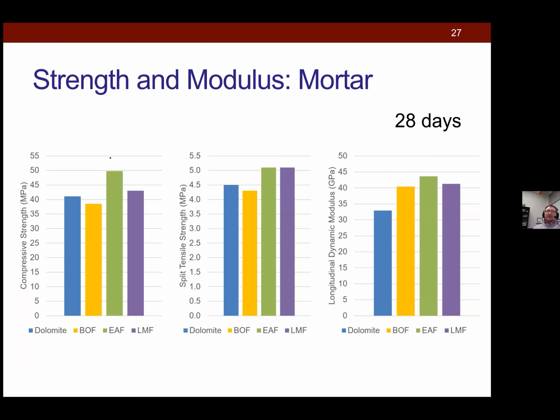So what we looked at a number of years ago was a handful of different sources of slag. Here are three different types of slag. We compared them to a control of dolomite, virgin aggregate. We pretty much found that there's a lot of variability. Depending on where the slag was coming from, you can get either an increase or a decrease in strength. In general, you seem to get an increase in modulus, probably because it's a higher modulus aggregate. Once you compound that with the composite modulus of the system, you increase the overall modulus. The problem is there's a lot of variability with this material.